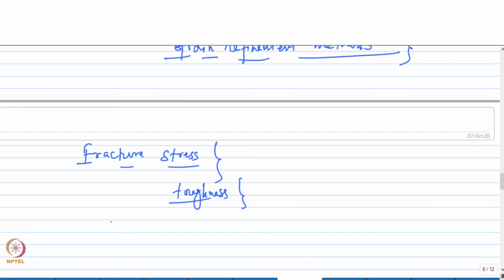Okay, but one property that will suffer due to grain refinement is creep, which is a time dependent high temperature deformation process, right? So one of the mechanisms of creep is through grain boundary sliding. So it is not difficult to understand that if the grain boundary area increases, the grain boundary sliding will also increase, and that will lead to more creep, and as a result, the creep resistance will come down as you refine the grain size.